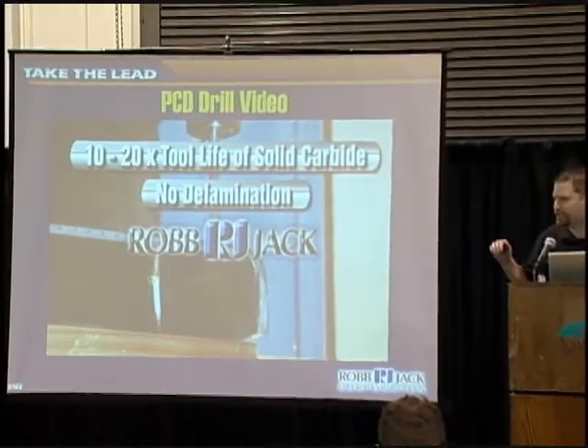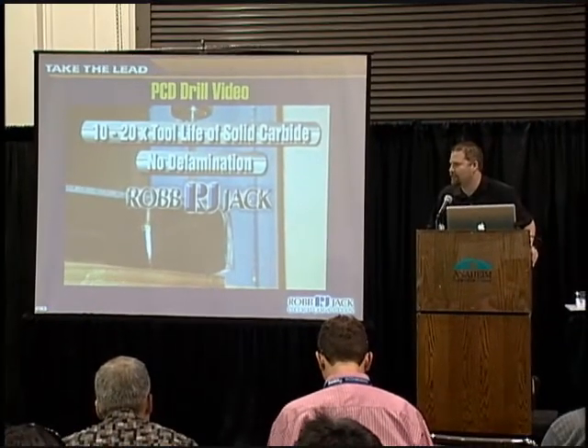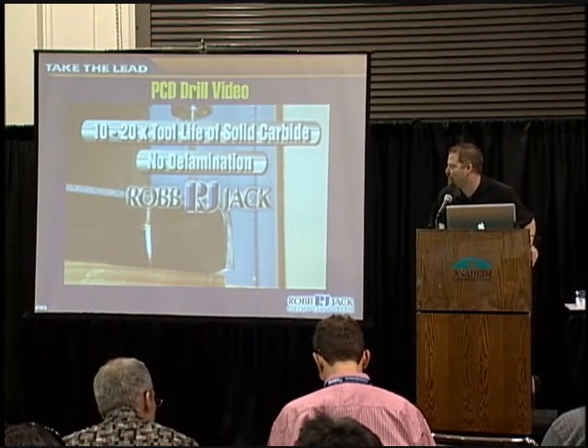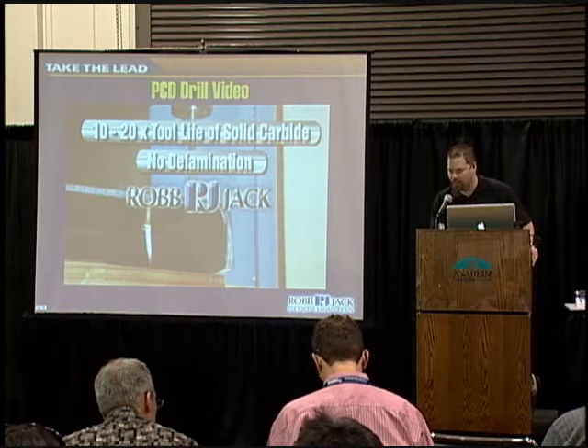So the advantage of using PCD or diamond coating is you get 10 to 20 times the tool life over carbide. And you don't get any of that delamination, none of the secondary work, hand sanding. You mill it, you drill it, and it's done. You don't have any of the problems that you would run into with using carbide drills.